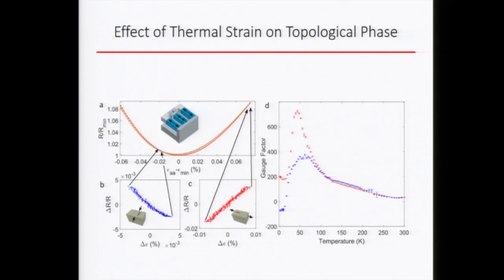The last thing I want to talk about on the strain stuff is that we do this experiment by gluing the crystal on a piezo stack. The piezo stack contracts along this direction and expands along this direction. When you glue a thin crystal, you're experiencing a thermal contraction from the substrate when you cool down, and for this crystal you'll get a tensile thermal expansion when you cool down. Then you can apply voltage on the piezo stack and locally vary the amount of thermal strain. And then we prove that when you glue the crystal in these different ways, you'll get an opposite slope, an opposite linear slope, corresponding to these two sides of the